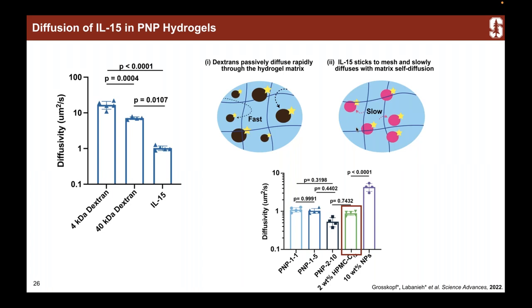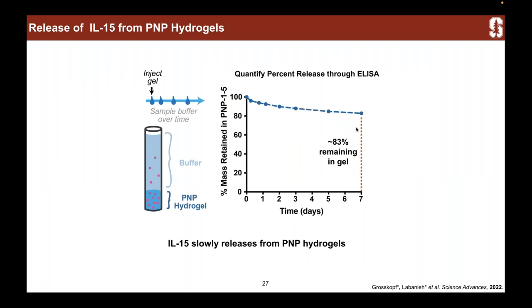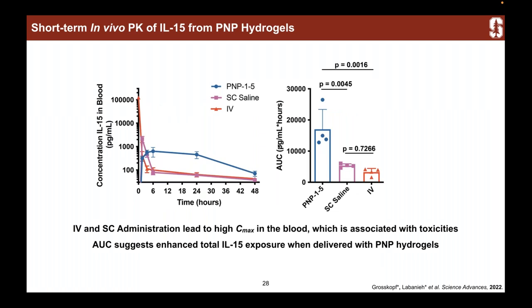This is really positive for our application because we want the cytokine to stay around as long as possible. I confirmed this by encapsulating IL-15 in the gel, putting buffer above it, and watching release into the buffer over time. Barely any actually released over the course of a week. We additionally confirmed these behaviors in vivo: IL-15 administered intravenously or subcutaneously was cleared very quickly in mice, whereas the concentration of IL-15 was much more steady over time in the PNP hydrogel — measurable through area under the curve.